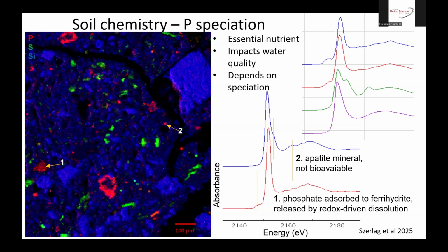The more distinct ones, like the one labeled 2, that's a spectrum that shows it's the mineral apatite. And the phosphorus speciation is important because it's an important nutrient for plants, but it's also, if it washes out of a soil into surface water, it can damage water quality, have algae blooms, be a pollution problem. So its behavior depends on its speciation. So you really want to know what it is at the microscale. And what's present in the bulk amount of phosphorus in the soil usually doesn't tell you anything about what its properties will be. That depends on the local speciation.